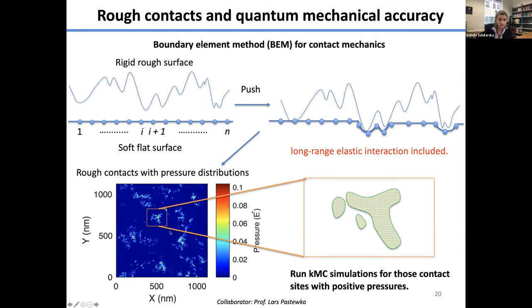So this is pressure distribution. You can see, of course, as expected, that the real contact area is much smaller than the nominal contact area. And then, so we know the pressure in these points, then we can take these and we can translate them into our kinetic Monte Carlo model, where we can consider chemical reactions of the interface. And so what it means is that we can truly combine the quantum mechanical accuracy of the chemical reactions that take place at the interface with a macroscopic model of deformation of rough surfaces to describe, in this case, aging of contacts on experimentally relevant time scales and length scales.